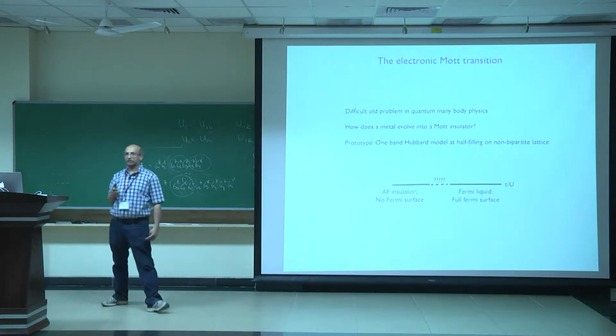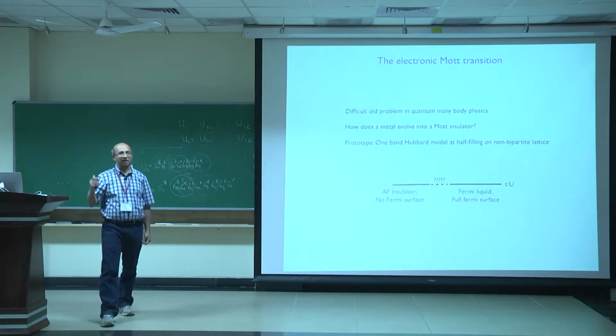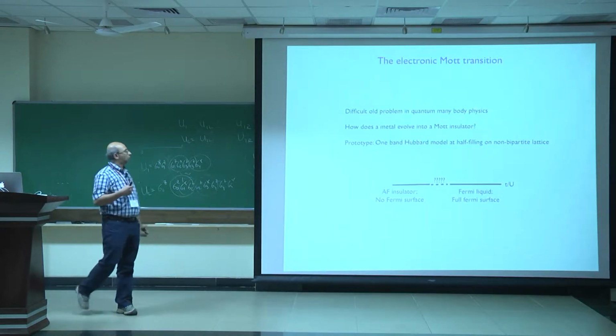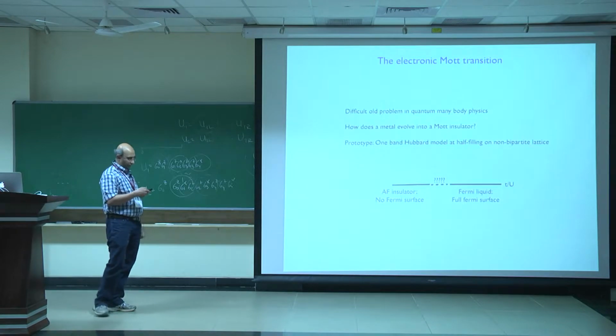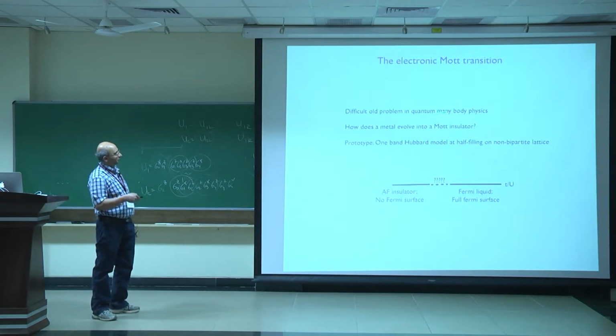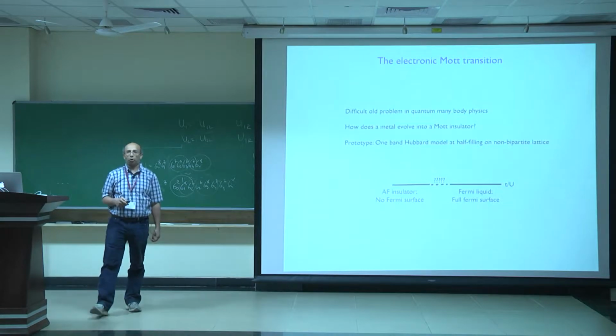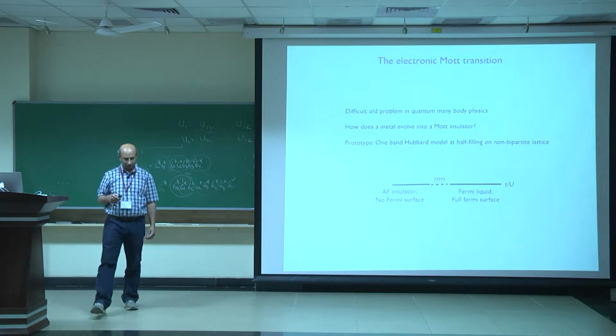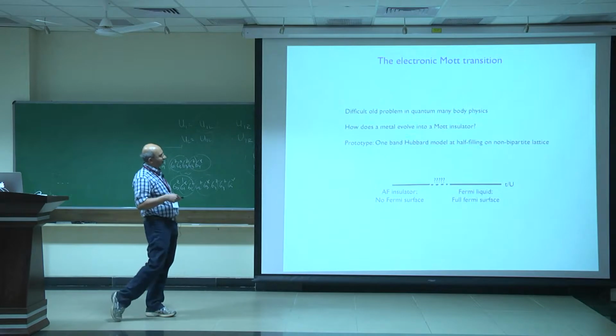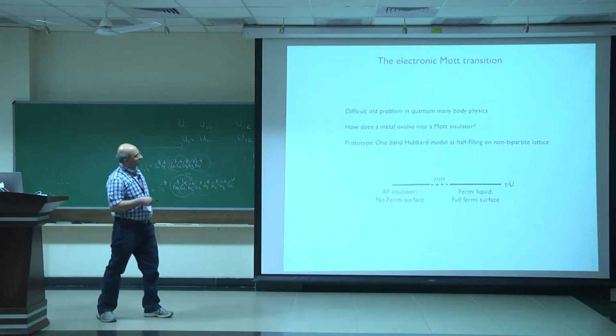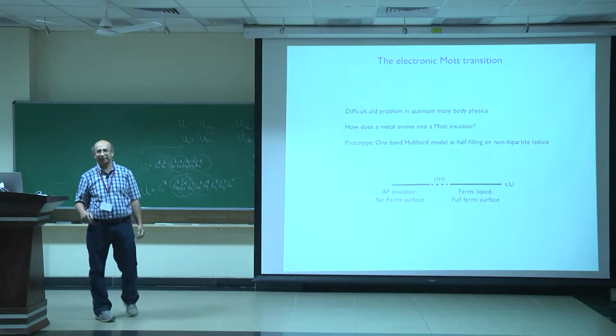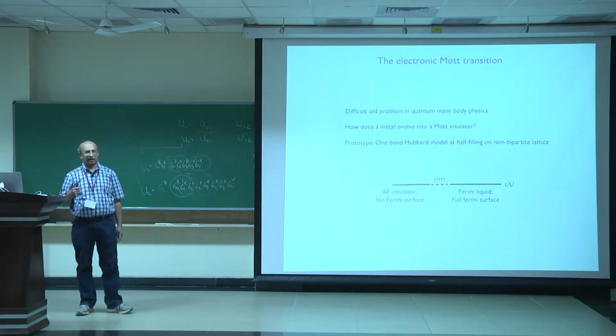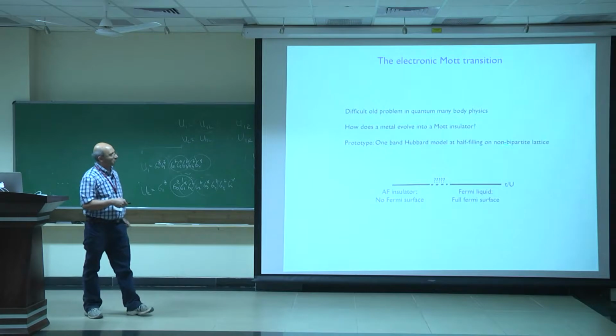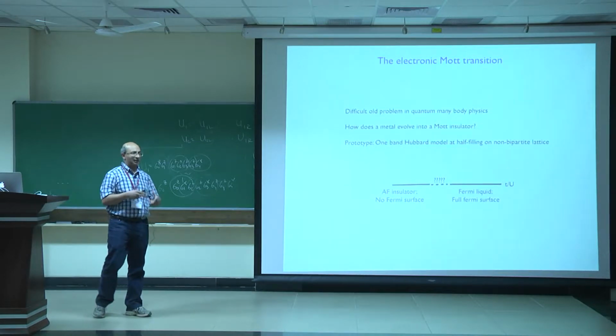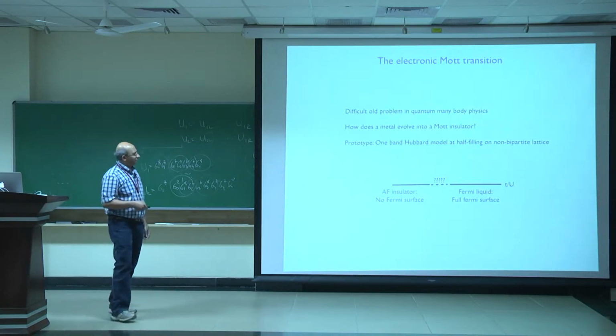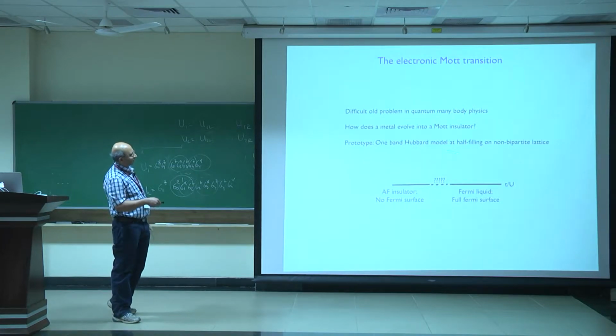So the electronic Mott transition is one of those ancient problems in the field that has never been solved. So the question is, how does a metal evolve into a Mott insulator? As a prototypical model to address this kind of question, one may want to write down, say, a 1-band Hubbard model at half filling, and so as to not deal with complications associated with Fermi surface nesting, it's convenient to study this problem on a non-bipartite lattice, for instance, on a triangular lattice. And so let's see what happens in this model.